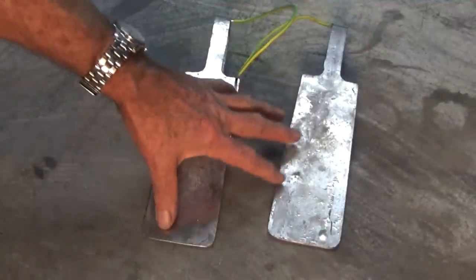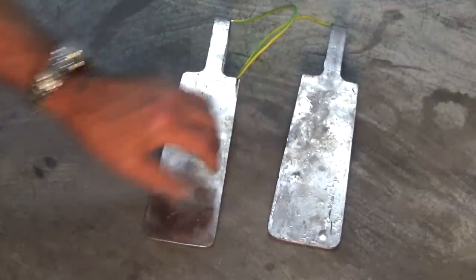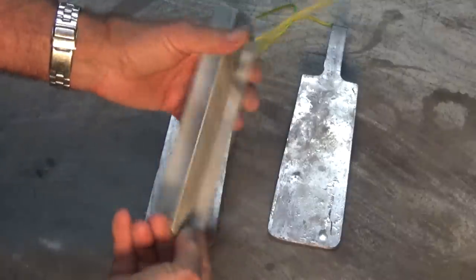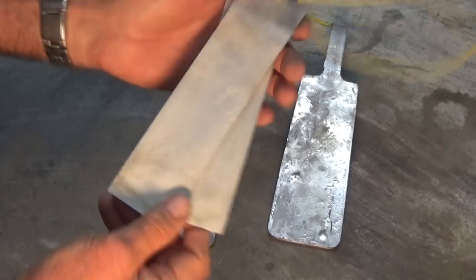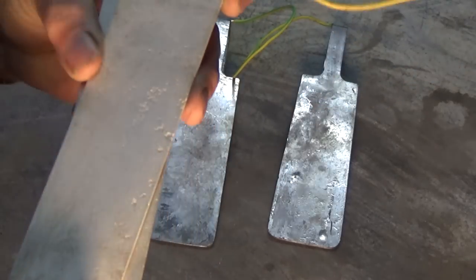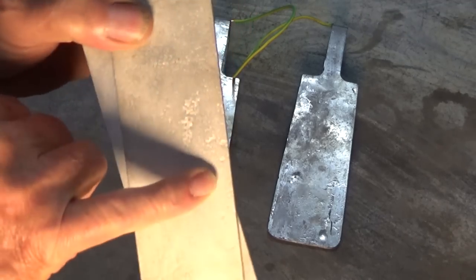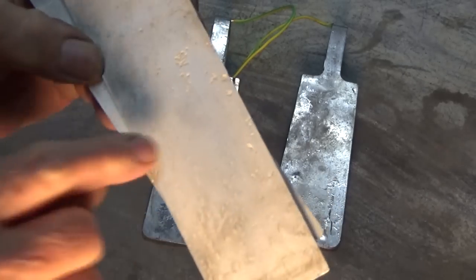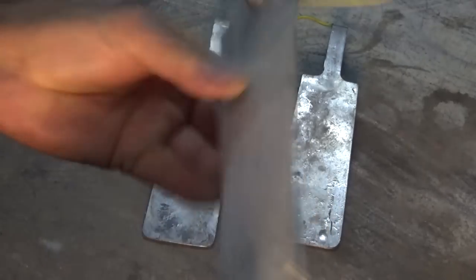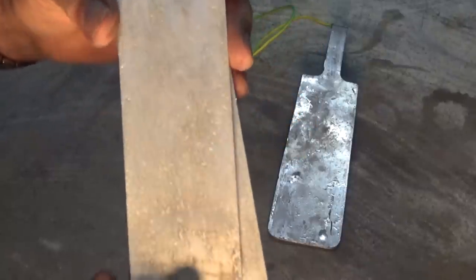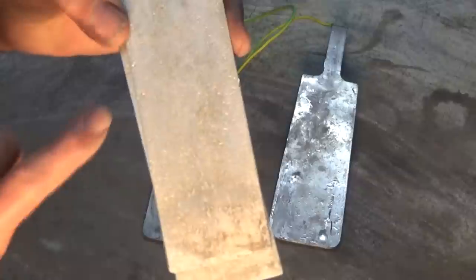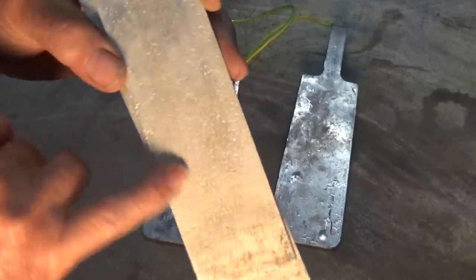Okay the next thing you'll need is cathodes. Cathodes used in anodising can be made of either aluminium or lead. When I first got started I was using aluminium, just a couple of strips. The problem with them is that they will gradually get consumed by the electrolyte in your anodising bath. These used to be pristine, they were shiny and smooth, now they're covered in craters and pits.